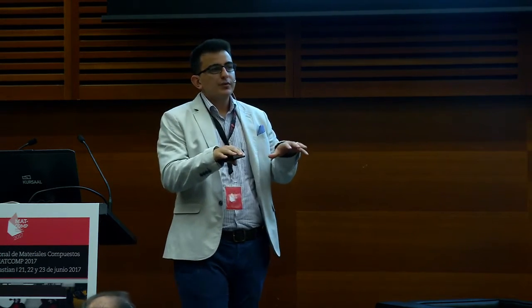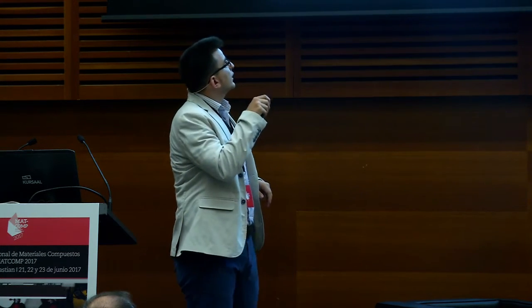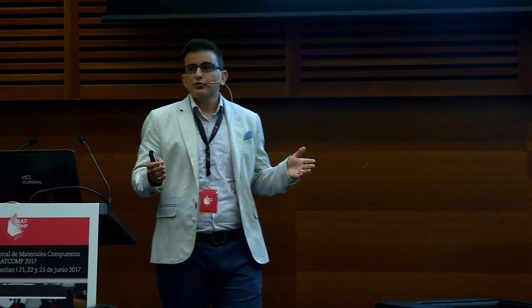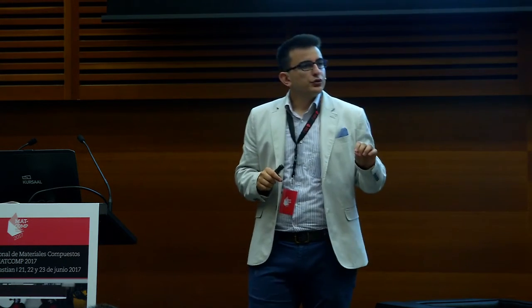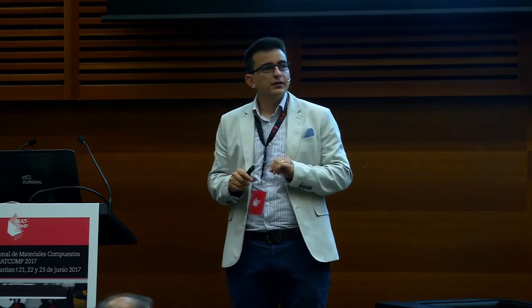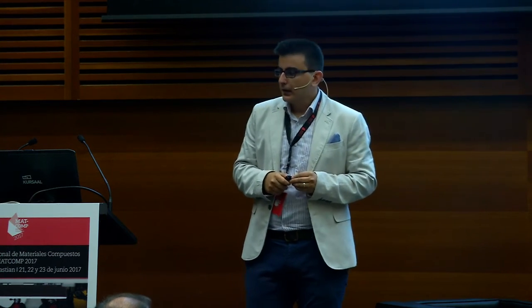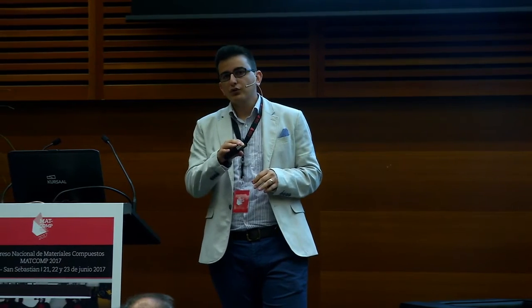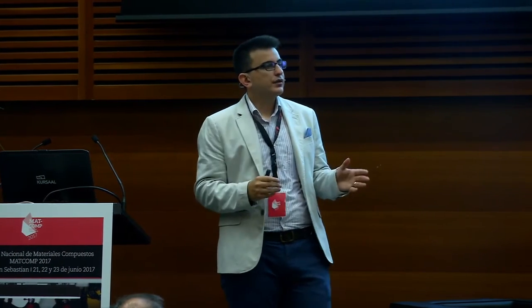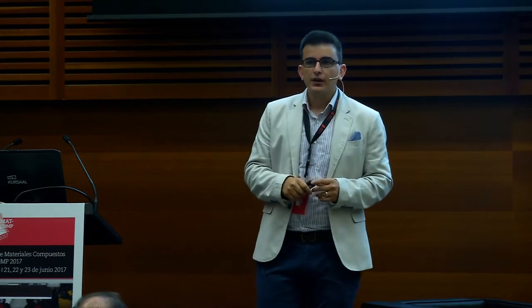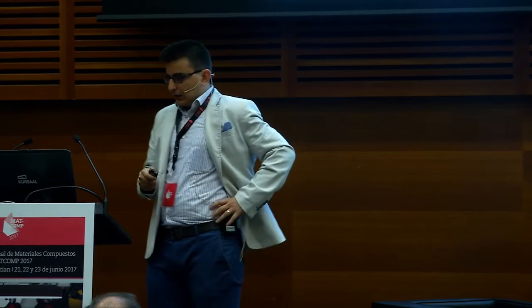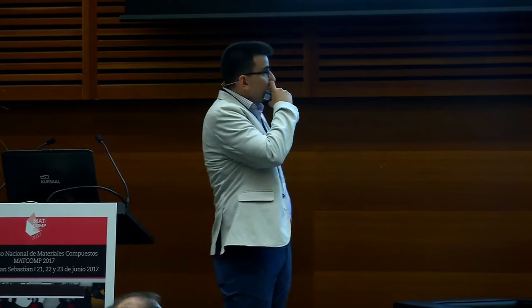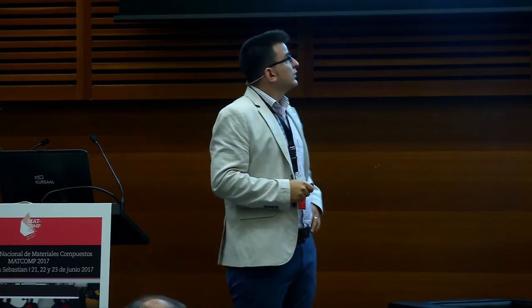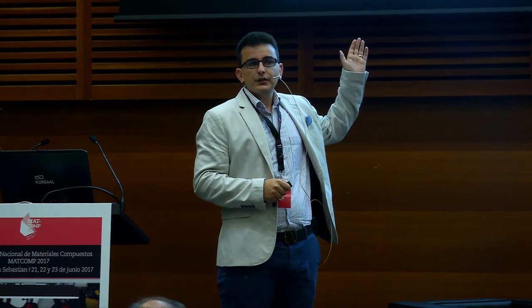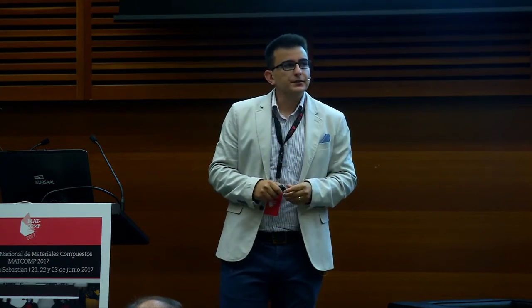And now in our deterministic optimization problem, we convert two of our constraints into probabilistic ones, such that during the process, the probability of degree of cure being less than 0.9 should not exceed 1%. And similarly, the probability of having maximum composite temperature being greater than 240 degrees C should not exceed 1%. So let's see what comes out from the optimization results. I show you a plot for probability of mean degree of cure at the die exit.